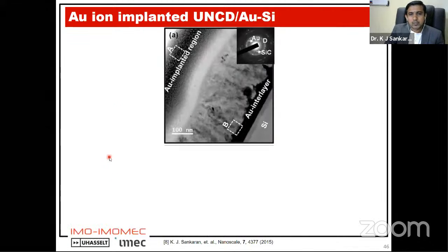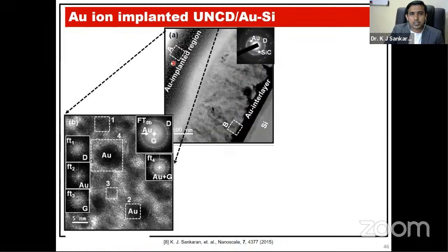So to know the reason, we carried out the TEM. This is the bright field TEM, which shows the gold implanted region and the gold interlayer region. If you see in the gold implanted region, there is the presence of gold here. These are the gold particles, and these are the diamond particles, also with some graphitic nature in the interface between the gold and the diamond.